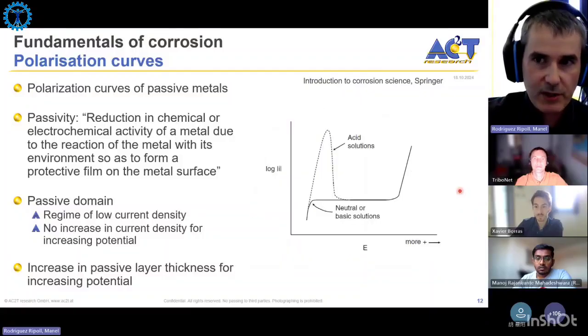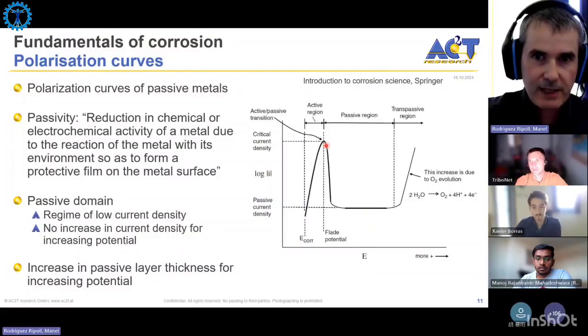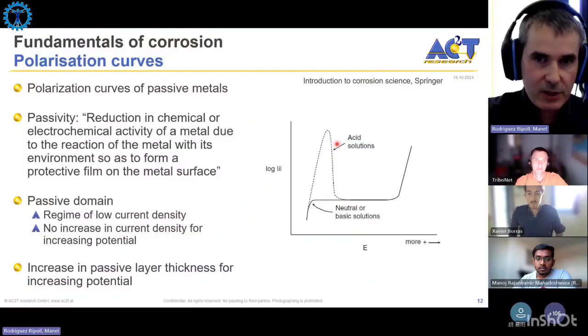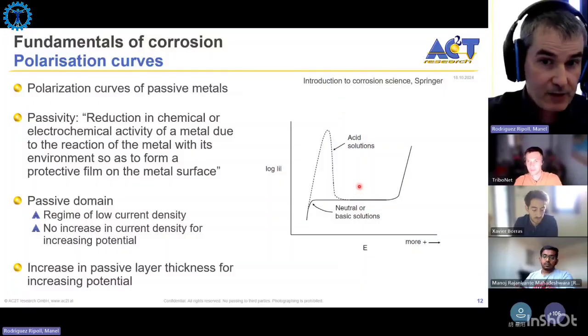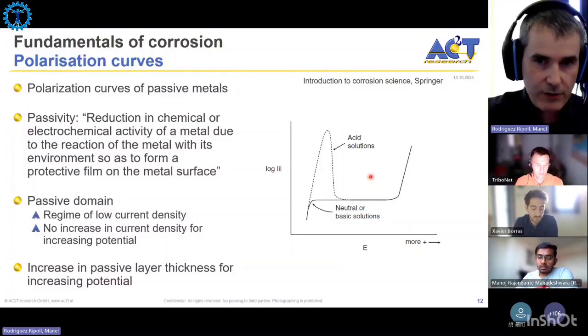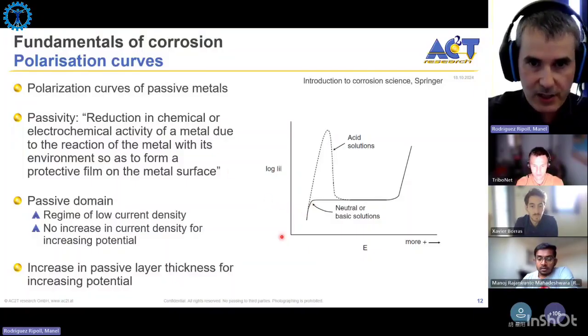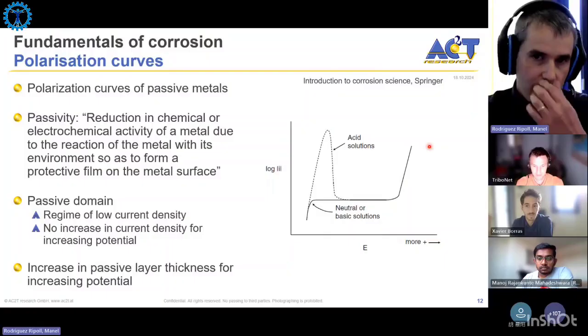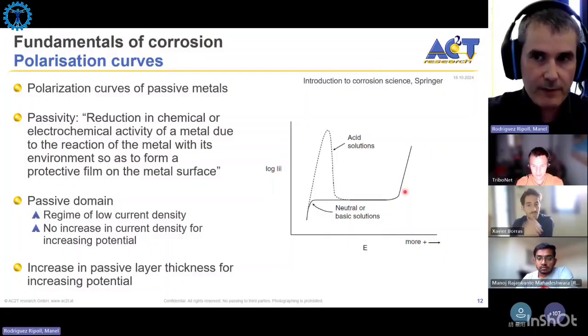So just for completing this, the active-passive transition does not always occur in all metals. It is often observed in acid solutions, but it's not obligatory to have it. It depends on the metal and the electrolyte. So in other metals or neutral solutions or basic solutions, you may go directly from the corrosion potential. So you have here the cathodic branch, then the corrosion potential, and then you may go directly into this passive domain, and then with increasing potential, you end up going into the transpassive domain.